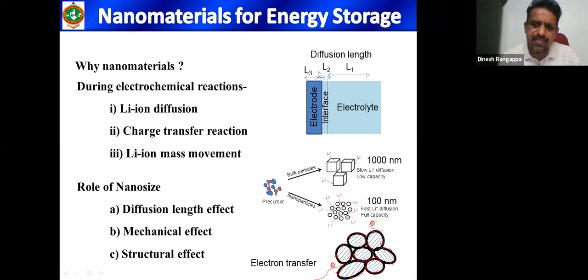So when you consider the different paths of lithium ion diffusion, then there is an electrolyte and electrode interface in between. L1 represents the lithium ion diffusion path in the electrolyte, that is solution diffusion, and L2 is electrolyte to interface region, where lithium ion from electrolyte diffuses to the interface region, and L3 is the solid state reaction, where lithium ions diffuse through the electrode crystal structure. So this diffusion in the solution electrolyte is fast, the interface is a little slow, but in the solid state in the electrode, it is a very slow process. Lithium ion diffusion process is very slow.